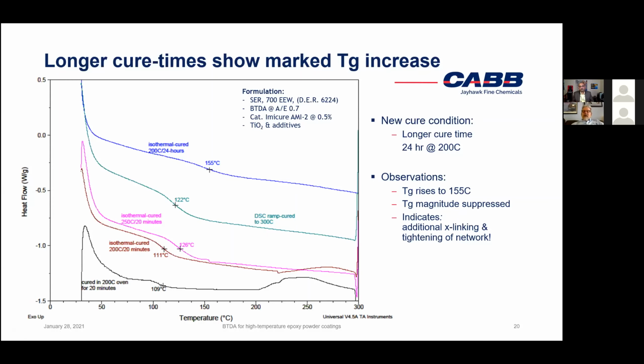So we were not able, beyond a certain point, to do the analysis of residual cure exotherms. You know, there's another just real quick thing. I'm not a polymer physicist, I'll give you that disclaimer right up front. But when I've posed this to polymer physicists and said, hey, is this thing still moving? They'll say, it's not going to be something that you can quantitatively measure with kinetic type analysis, but it could be morphological. Realistically, there may be morphological changes that are starting to move the T sub G, independent of residual cure, incompleteness of cure. Just something to tuck away.